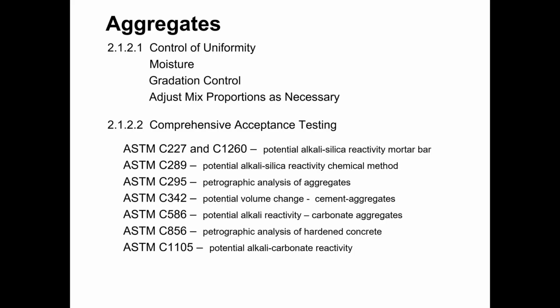Now keep in mind that the reactivity of the aggregate is of primary concern to us, but there are also other things of concern that the petrographic analysis could give us an indication of. One of those may be the amount of iron in the sample. Iron in an aggregate sample tends to cause rust stains over time, and that usually doesn't adversely affect the structural performance of the concrete, but it certainly affects the aesthetic performance of the concrete. So that's something that would be good to know. So petrographic analysis is not just to give an early indicator of reactivity, it also gives an indicator of other potential issues.